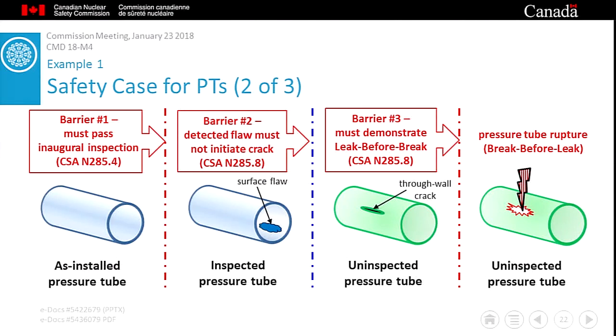Considering these figures in turn, on the left-hand side of the figure we see a new pressure tube that is yet to begin service. To qualify for installation, the tube must be designed in accordance with the CSA standard. The tube must be installed per utility procedures and then be subject to an inaugural inspection in accordance with another CSA standard. If CNSC staff is satisfied with the results of this inspection, barrier 1 has been crossed, so the pressure tube can begin service. Moving to the right, we see the inside surface of the same pressure tube where a flaw has developed.